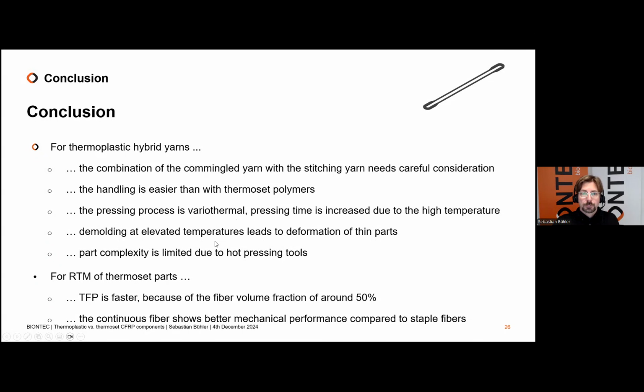Demolding at elevated temperature leads to a deformation of thin parts, as I mentioned before. As you can see here, the part is very thin. If we would have a bigger part, then I think the deformation and the warping would be less. Also, we see that the complexity of the hot pressing tool is limited because,